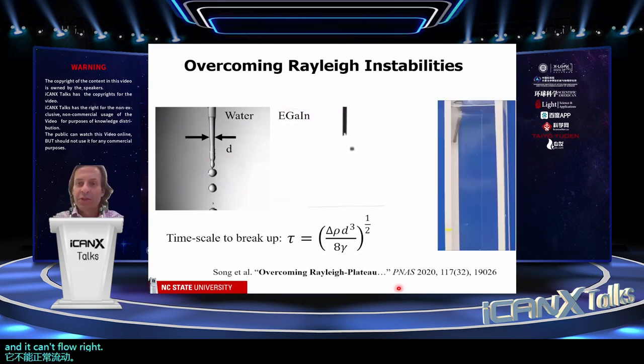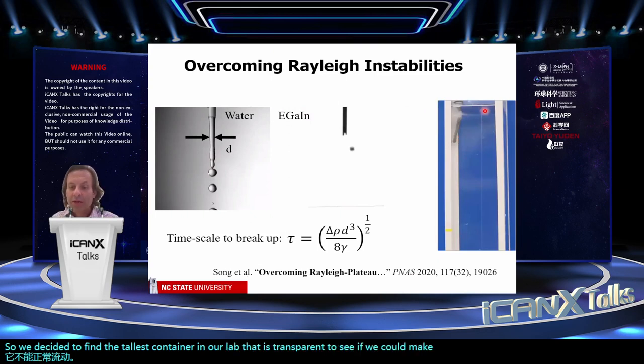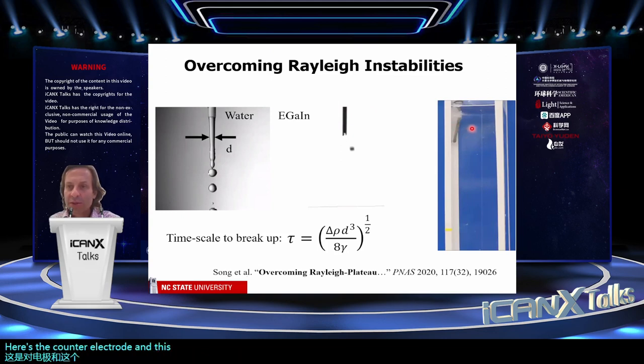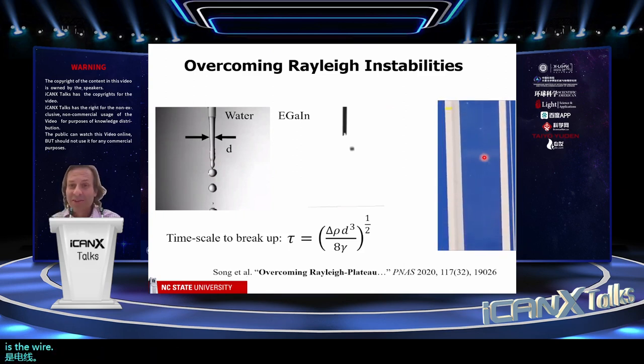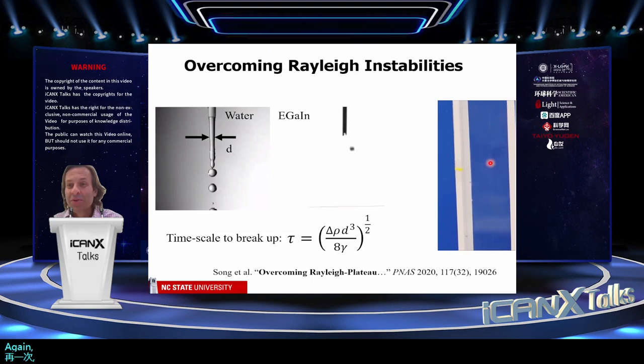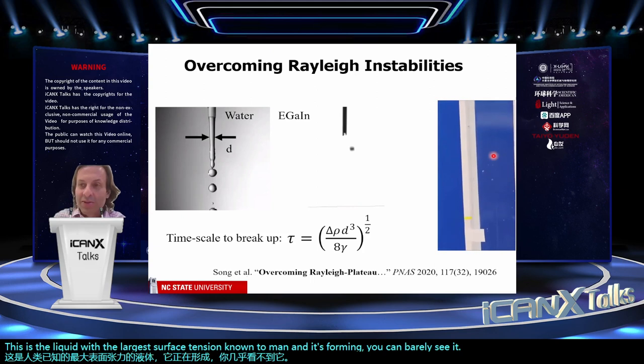So we decided to find the tallest container in our lab that is transparent to see if we can make these things really long. So here's our nozzle. Again, it looks like this. It's 100 microns, the size of a human hair. Here's the counter electrode, and this material is sodium hydroxide. So I'm going to point to this wire. I'm going to let this video play, but where I'm pointing is the wire. This is incredible because, again, this is the liquid with the largest surface tension known to man, and it's forming, I mean, you can barely see it, and it's forming this very long wire, even though the surface tension should be very large. So again, this is happening because of oxidation.